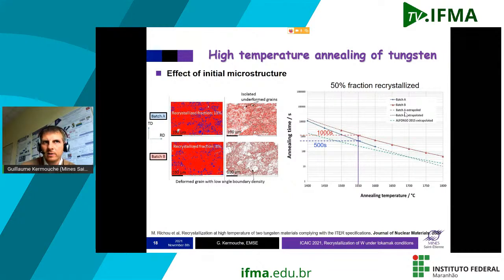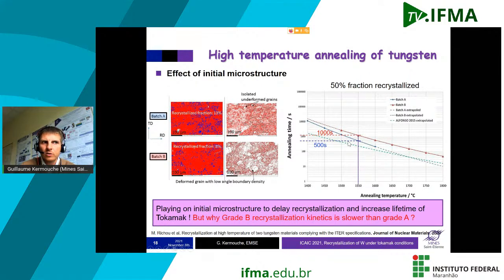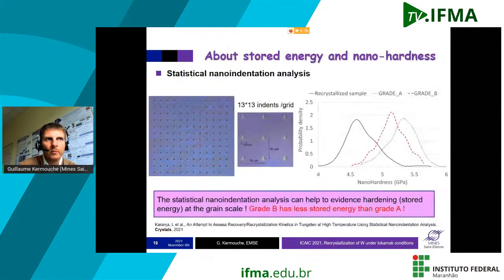So regarding PFU lifetime, it's better to use batch B materials. The question is why grade B recrystallization kinetics is slower than grade A. So we can answer that question by using some measurement at the microstructure scale. Basically it's based on hardness measurement, but not macroscopic hardness, what we call nano indentation, so nano hardness.